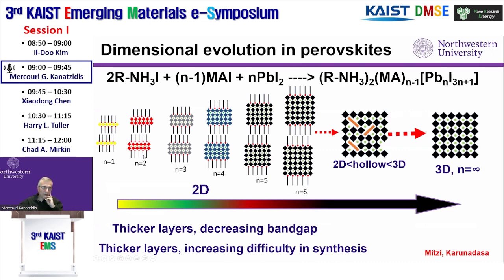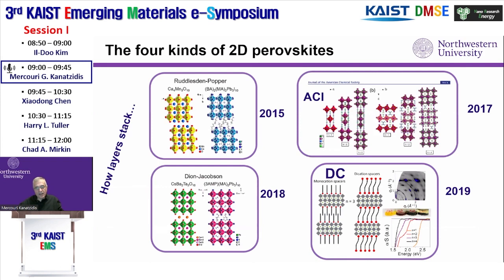And so if you control the synthesis, you can make many members, anywhere from, in this series, n equal 1, which is only one layer of perovskite, to n equal 2, you get 2, and then 3 gets thicker and thicker, and then all the way to 7. And so in a way, some people call these quantum wells because of alternating band gaps between the perovskite and the spacer. And of course, the properties approach that of the 3D. And in the middle, we also discovered a hollow version, which is not quite 3D because it's hollow, but not quite 2D. So those are interesting as well. So here's 4 different kinds of 2D perovskites.